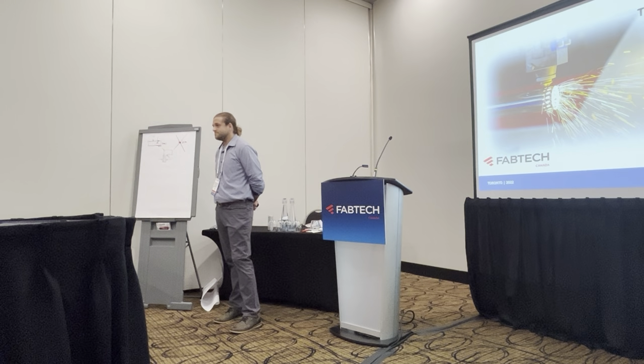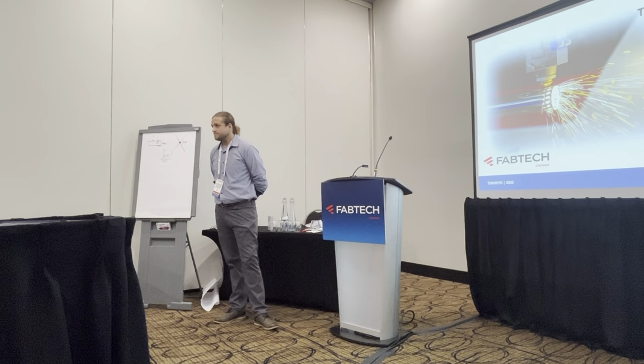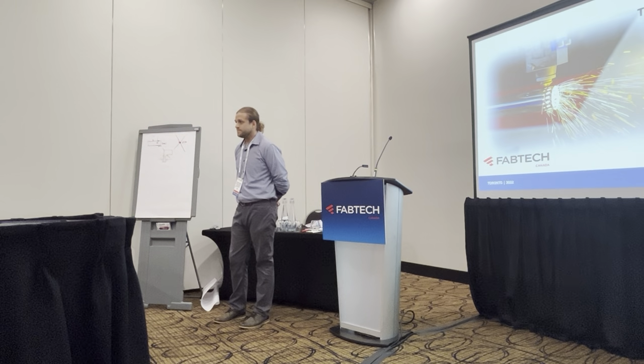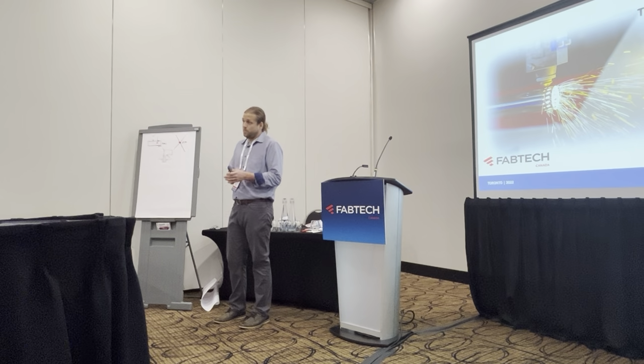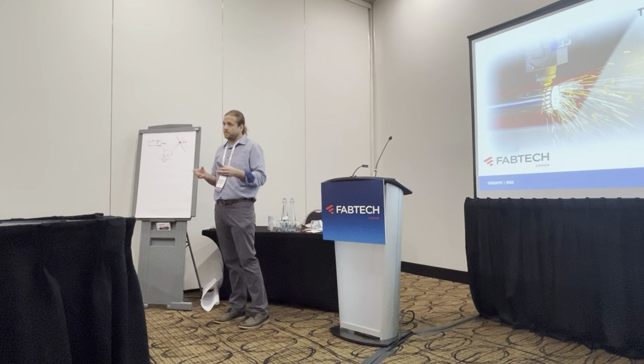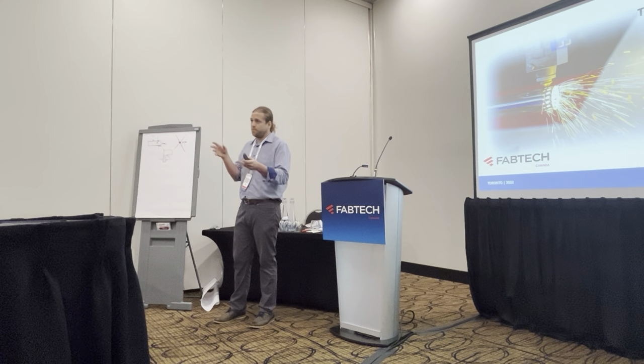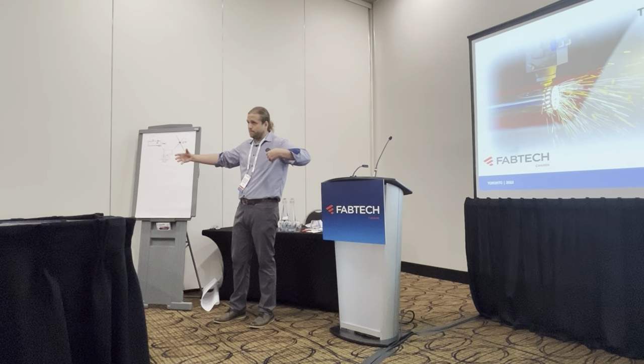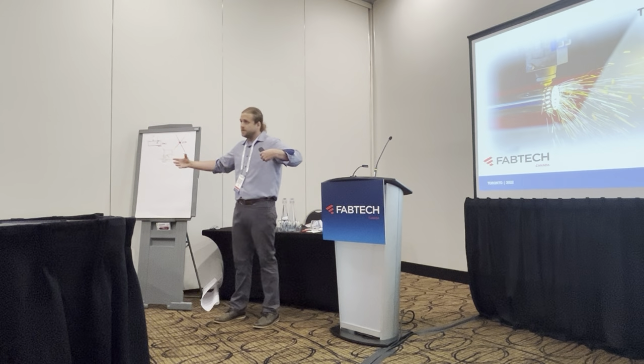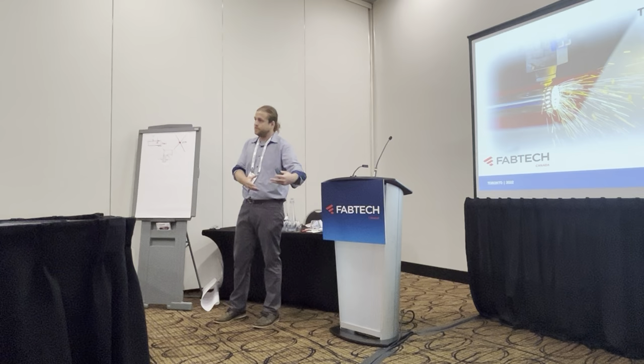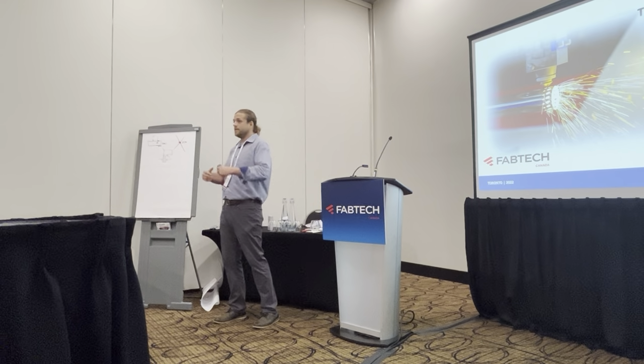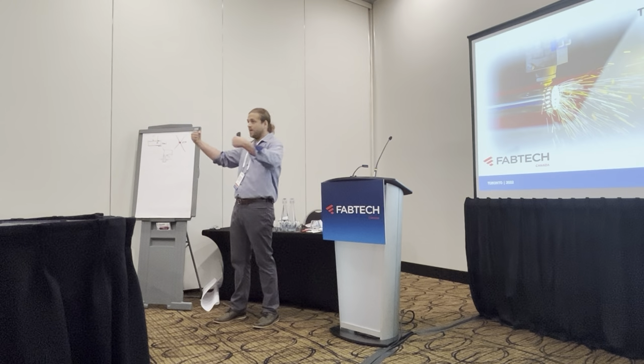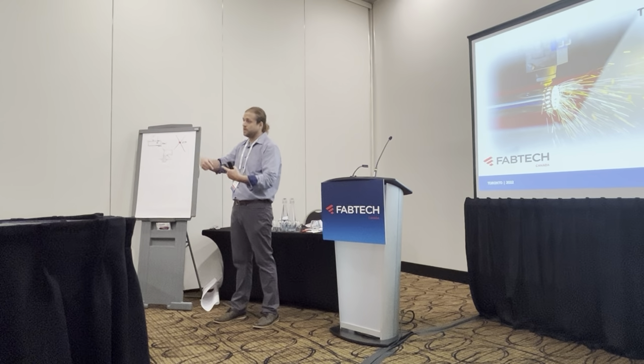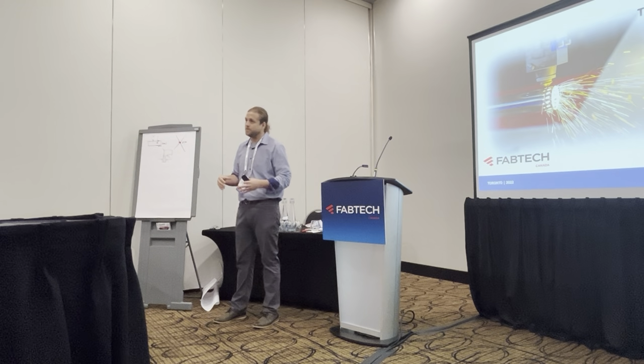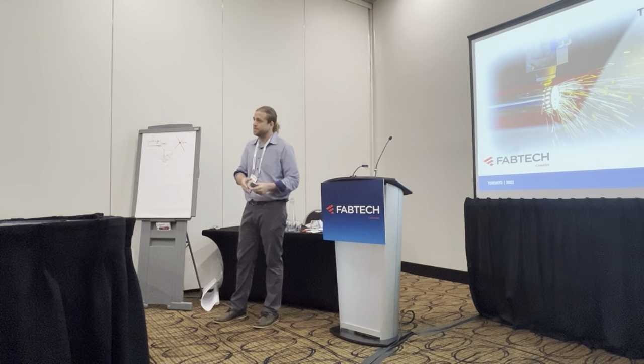Yeah, because I just saw a video that they cut the rectangular tube bend uniform and then weld it. Yep, that can be, I've done it both ways. So on laser, you can actually cut the reliefs, and we've done it for prototyping and production. Actually, a trailer hitch, they wanted it bent on a very odd centerline radius. And when we approached them, we said, well, this is your cost to achieve that. However, we can cut the reliefs on the laser and then hand form it, and then you can close those up in your weld fixture when you're applying all the other components to it. And we ended up going that route versus actually bending it.